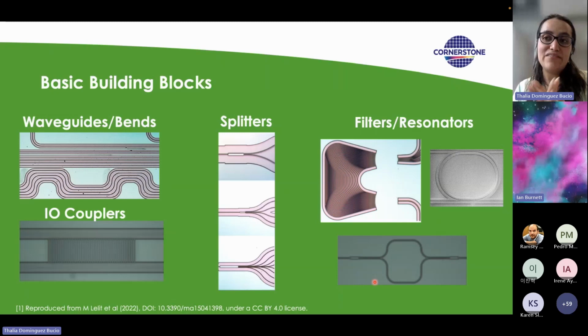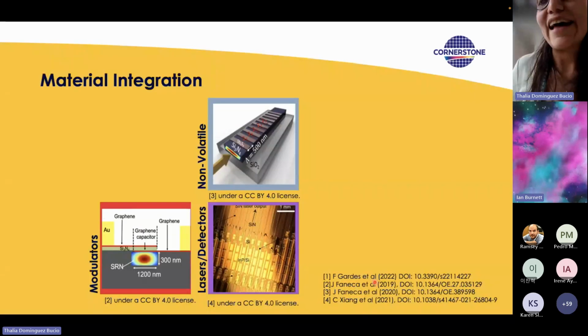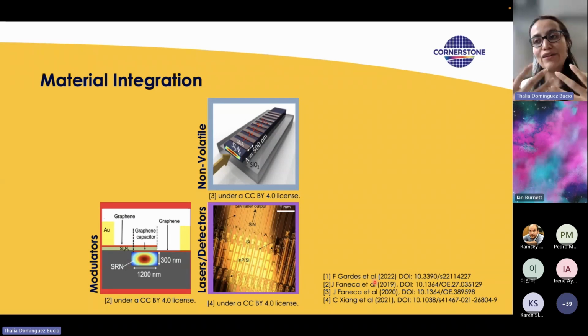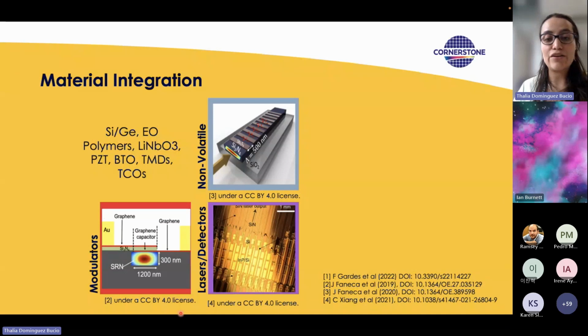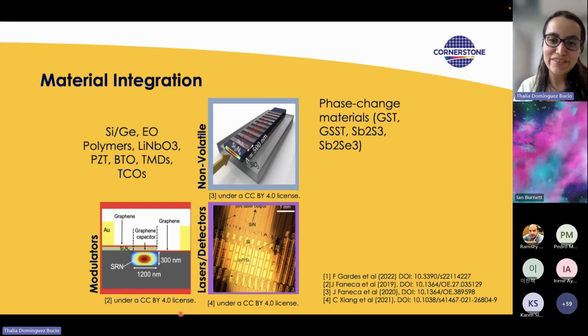Here I'm just mentioning passive devices. That's one of the caveats of silicon nitride: although it's very good for many things, it can only be useful for fabricating passive devices. So if we wanted to add active functionalities to the silicon nitride layers, we need to integrate these silicon nitride layers with other materials. We can achieve modulation by integrating our nitride with silicon germanium stacks, electro-optic polymers, lithium niobate, BTO, transition metal dichalcogenides, and transparent conductive oxides. We can also create some non-volatile devices by adding phase change materials, or we can integrate lasers and detectors by incorporating our silicon nitride with III-V materials.